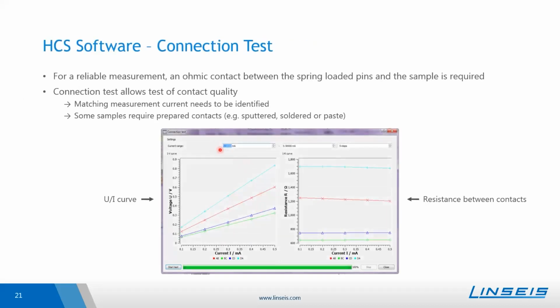With this tool, you can set up a current range with the lower and the upper limits and the number of steps in between, so that the system will linearly increase the current and measure the voltage, so that you will get a UI curve as indicated here. In case of an ohmic contact, you see a linear behavior. Additionally, the resistance is calculated in dependence on current, and in the ideal case, the resistance does not change that much. So this is also an indication of the quality of the contact.